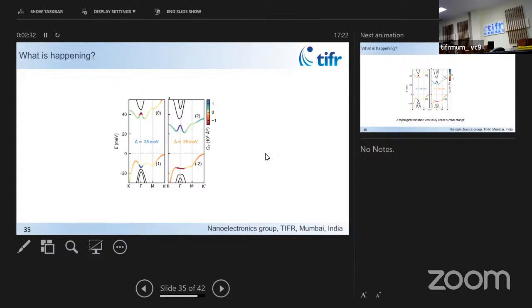From our inference from the experimental data, I think maybe some confirmation, we see some strain which is less than 1%, maybe 0.5 or 0.2%. Maybe I'm blanking out on the number. 0.1. So it's a very small amount of strain. You don't need a whole lot to break that symmetry. Amit's group did lots of calculations on the magnitude of the strain. The magnitude of the Berry curvature dipole scales with the strain, but the physics is still robust. So it's actually a relatively small strain.